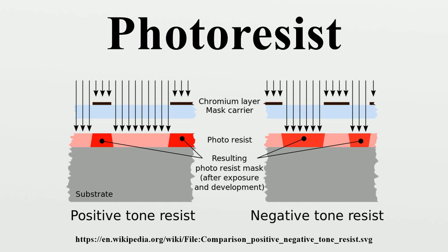Photoacid generator: The e⁻ represents a solvated electron, or a freed electron that may react with other constituents of the solution. It typically travels a distance on the order of many nanometers before being contained. Such a large travel distance is consistent with the release of electrons through thick oxide in UV-erase operations in response to ultraviolet light. This parasitic exposure would degrade the resolution of the photoresist. For 193 nm, the optical resolution is the limiting factor anyway. But for electron beam lithography or EUVL, it is the electron range that determines the resolution rather than the optics.